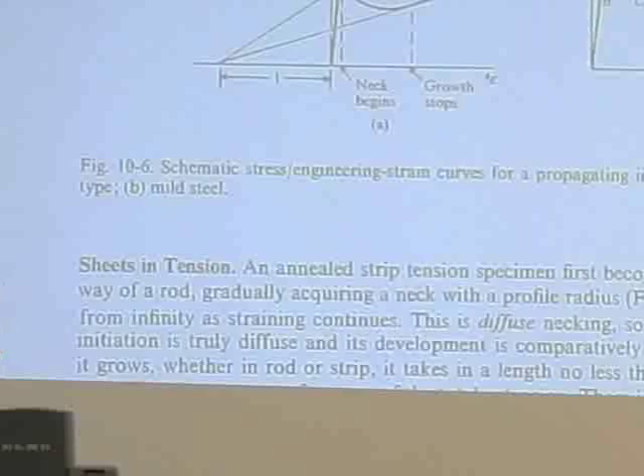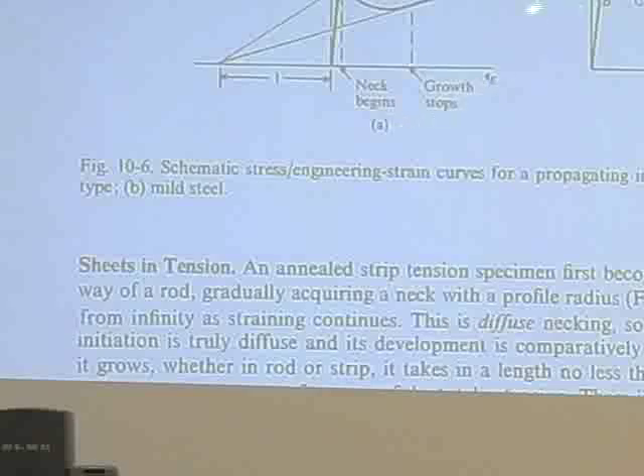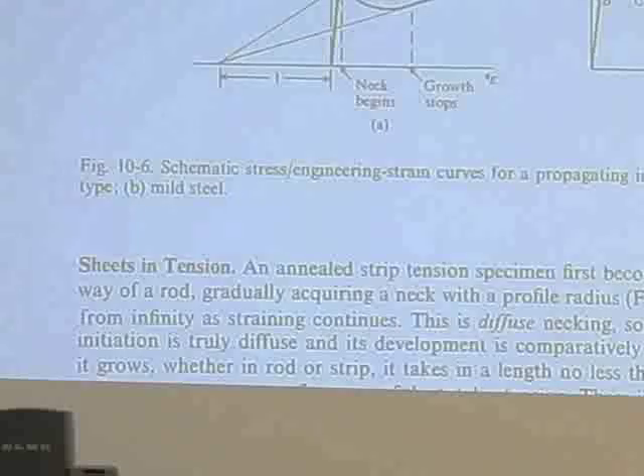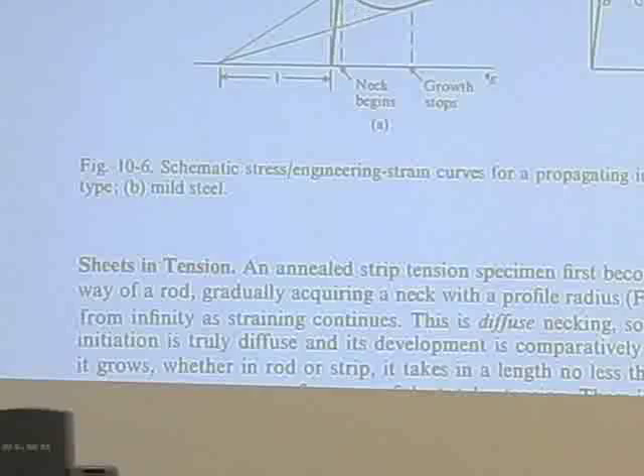Well, what happens when you have a polymer or a metal that has an upper and a lower yield point, and you do a constant rate of extension? You have the neck begin, which is just geometric softening versus material work hardening. Whenever the curve turns over, it's starting to get softer. When the work hardening goes negative, it's definitely getting softer. The hardening becomes softening, and you'll get a strain, and that strain will propagate itself right through the material as a little thin down region.